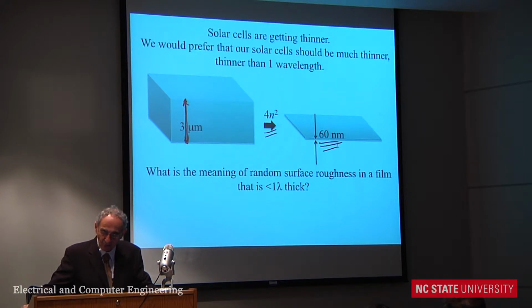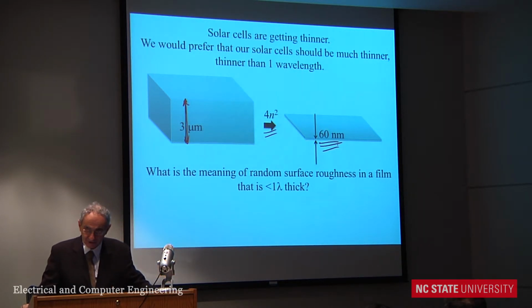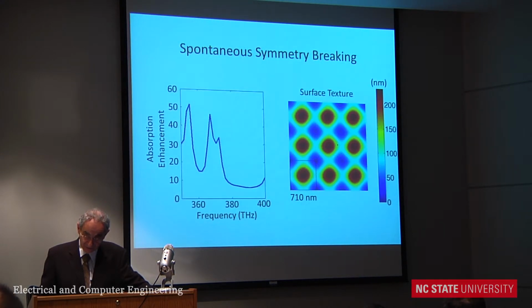And so at that point, I think you have to have some kind of deterministic pattern. And so that becomes a situation, and most likely that deterministic pattern will satisfy periodic boundary conditions and will indeed be a two-dimensional photonic crystal. So I assigned the problem to a student, and the problem was: find the texture on a thin film, just thin film optics, but should have some texture to it. Find the texture that ends up absorbing the greatest amount of light.